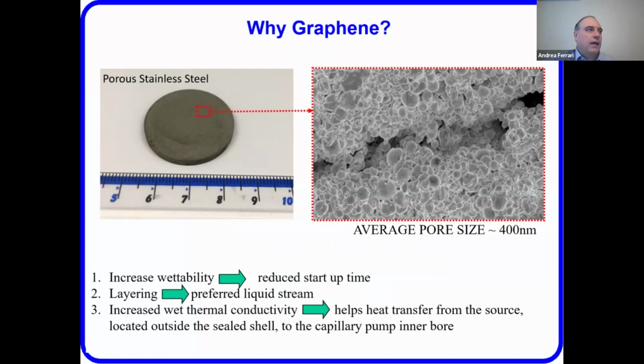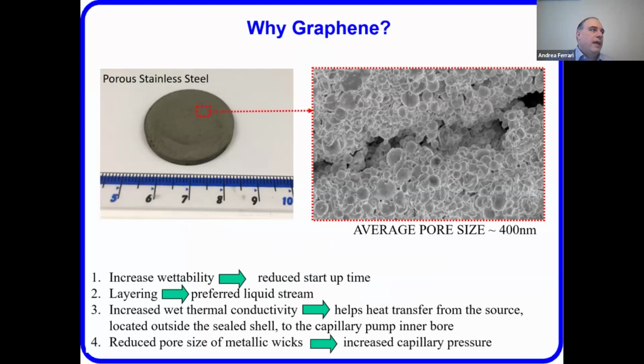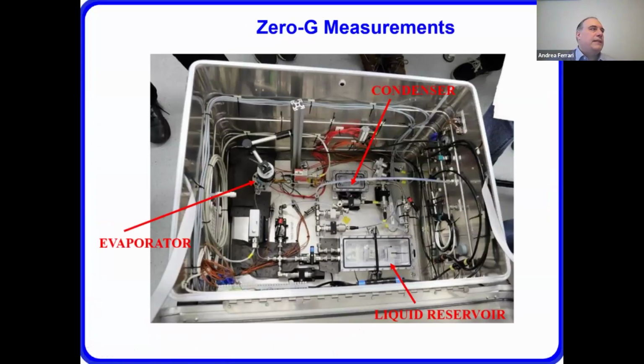Another effect is that graphene reduces a little bit the size of the pores because it coats them, and this increases the capillary pressure. So this is the first system that was tested - it was in a box with a condenser, an evaporator, and everything else.